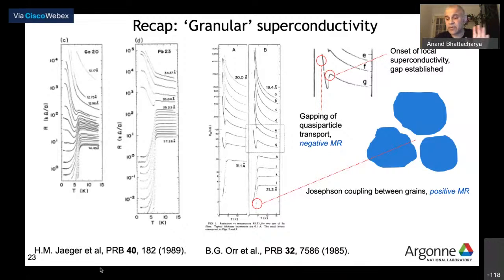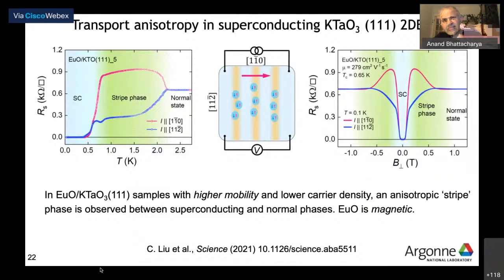So this is a very well-known piece of physics where you have grains that are superconducting, the electrons experience the superconducting gap as a gap for quasi-particle excitations, and then the transport becomes activated, like you're saying, becomes insulating. The neat thing here, though, is that in this data, in one direction it is not granular. In the other direction, it is granular.